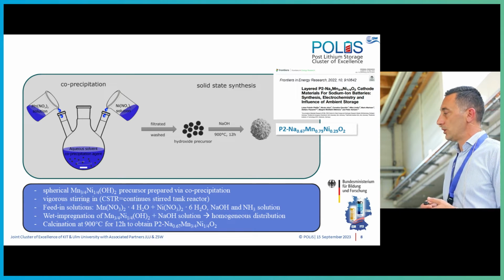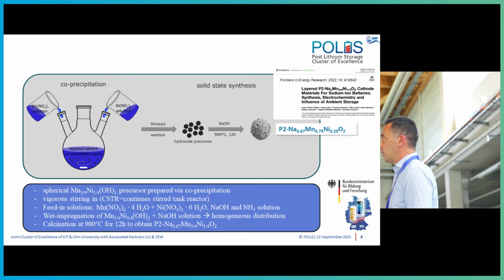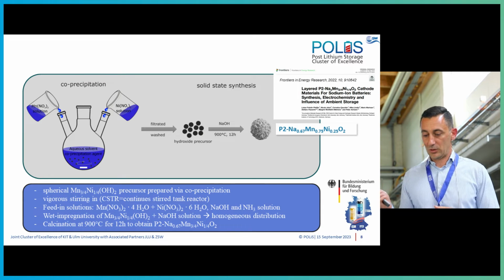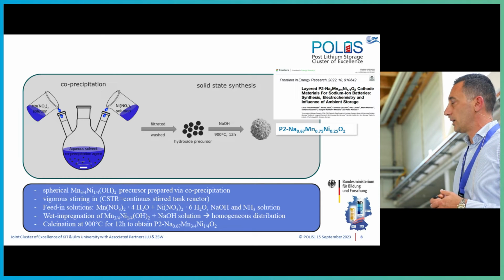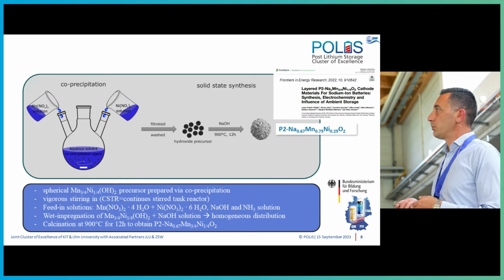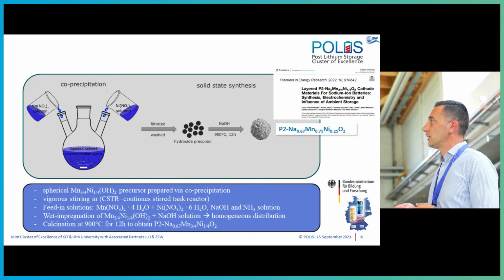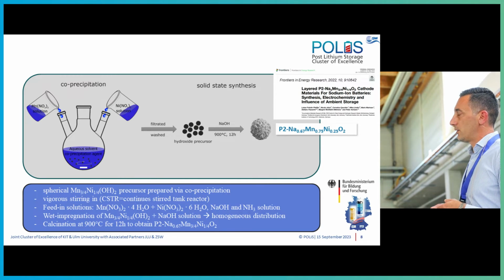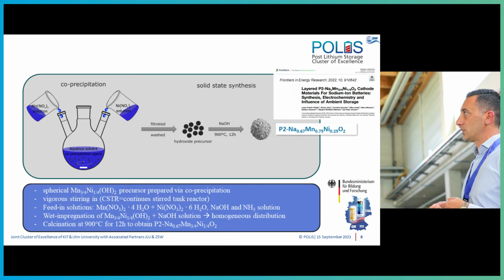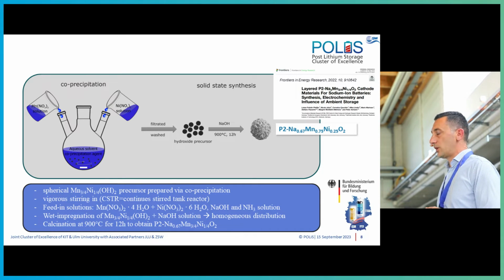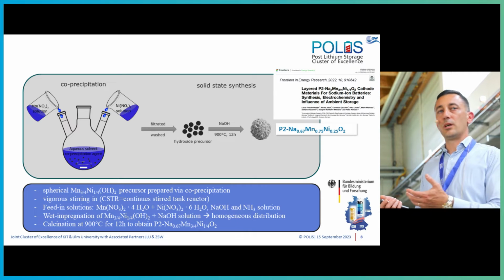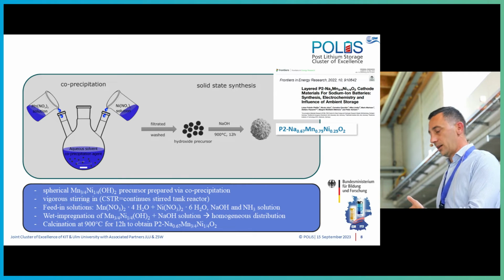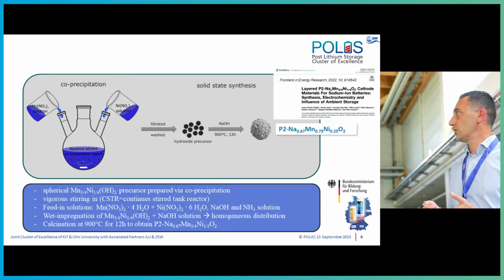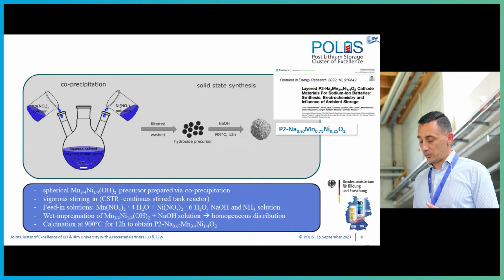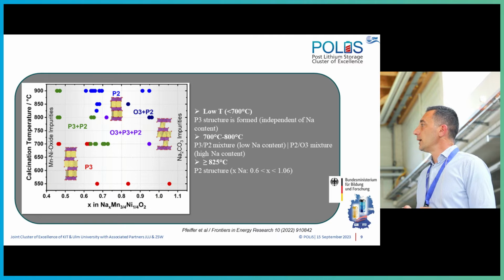Okay, so of course we went into co-precipitation using two of the transition metal precursors in the form of nitrate. Of course, we put everything in a flask, stirring, and then we get the first hydroxide precursor, which is then followed by a solid state synthesis, so impregnation with the sodium hydroxide, and then heat treatment at 900 degrees C for 12 hours. And this is what we get: spherical particles in the range of 20 to 30 nanometers.